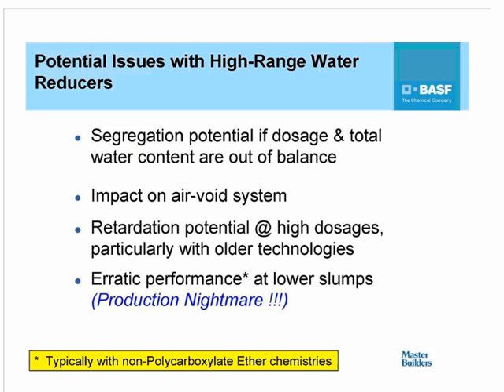However, just like any of the other admixtures I talked about so far, there are some potential issues, which could be segregation if the dosage that's used is not in balance with the total water content of the mix. In addition, especially with the older technologies, high-range water-reducing admixtures can potentially also lead to some amount of retardation. This is not that much of an issue these days with the newer polycarboxylate ether technologies. Also, high-range water-reducing admixtures, when used at lower slumps, can lead to erratic performance.